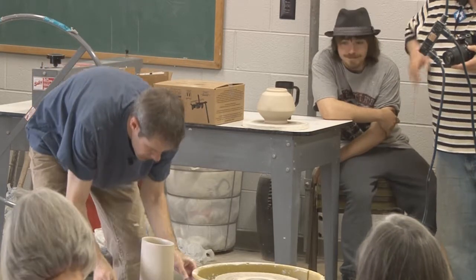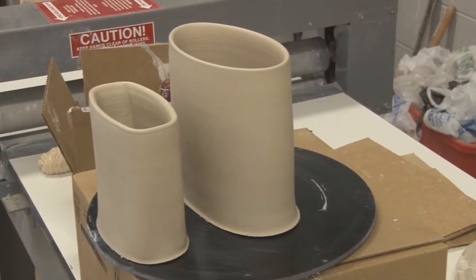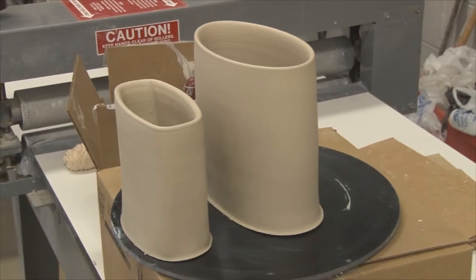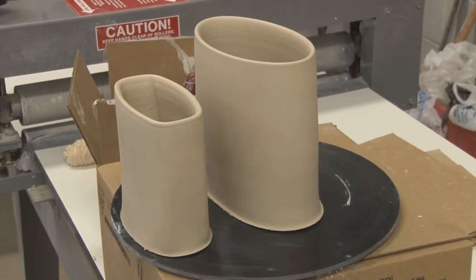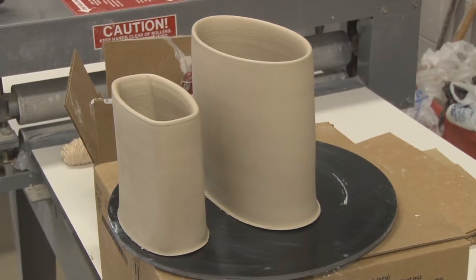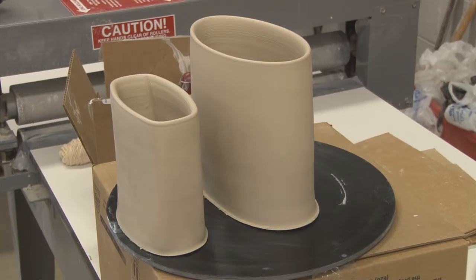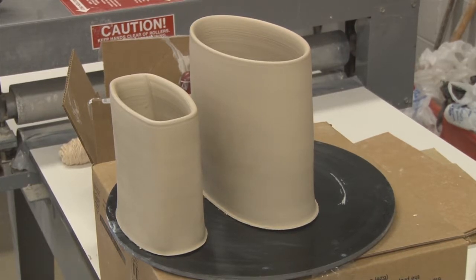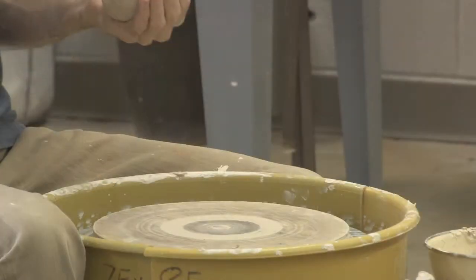You guys also want to see me, so I'll just squeeze that around. And this is what I found, is that sometimes I get cracks here. What happens is as I push it in and it flares back out, I'm basically compressing the clay and it's uncompressing on that inner edge, and it'll crack later. And it's typically in the bisque firing at a time when I can't make any repairs to it. So I try not to squeeze them. I was trying to get them really narrow, with all these problems with cracking. So I decided I wasn't going to push them as far, and I've had more success. And I'll make a little one too to go along with this.